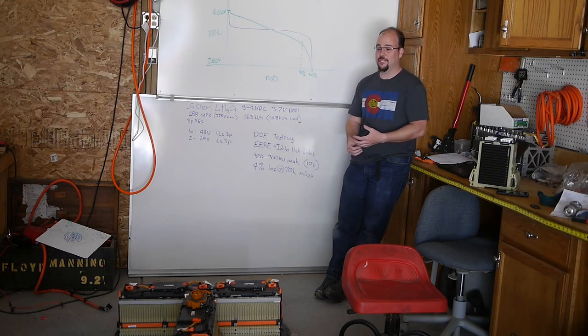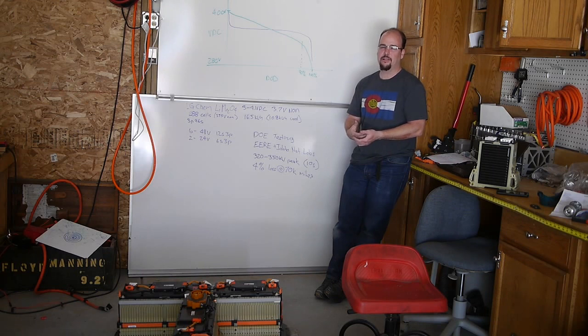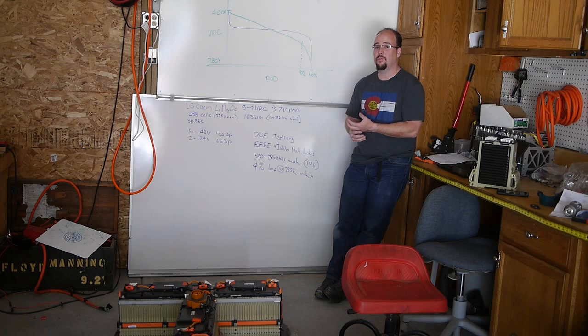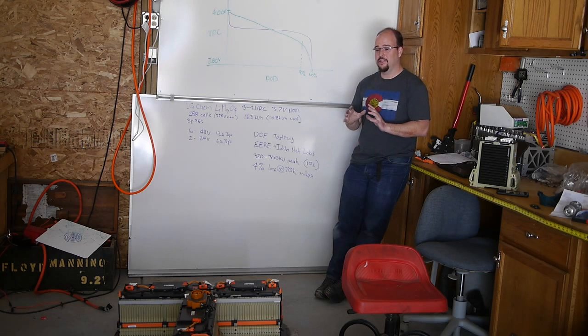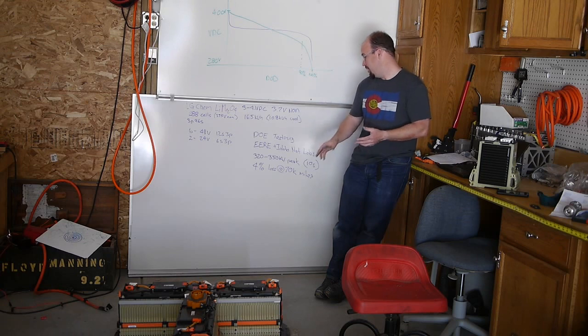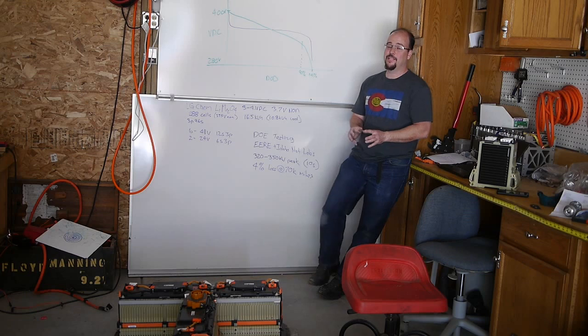Most Volt owners, like myself, try to use the electricity all the time. For me, I've got 50,000 miles on my pack that is cycling twice a day, full charge, discharge, thereabouts. And that's typically the way to run. Fortunately for the test that's available, that 70,000 mile one, it's probably almost all exclusively EV miles. And so with that, they're showing a 4% loss at 70,000 miles. So that's pretty good.